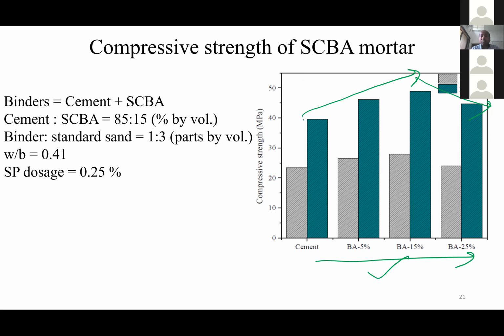For example, when compared with control, almost there is a 6 to 7, 8 MPa increment in strength. Okay. Now, many times we miss one important point. Always we highlight that the 15% is the best combination. Please understand, on a sustainability note, actually I would insist to go with 25%.